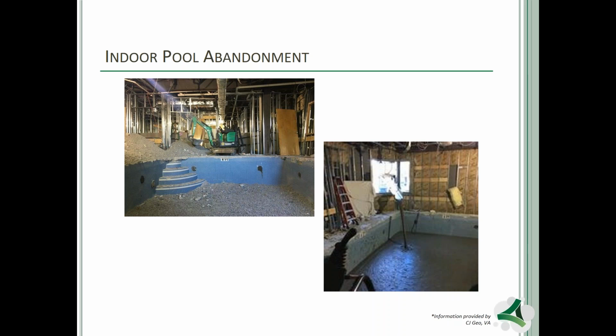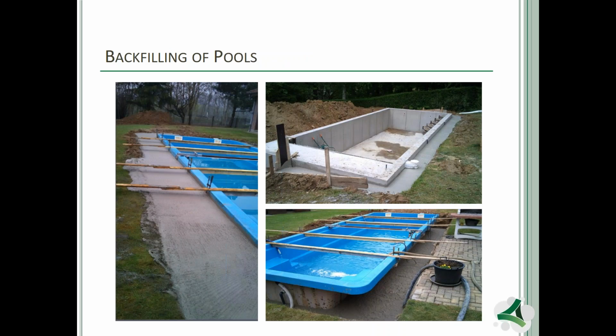Another abandonment scenario was an indoor pool being abandoned from an old therapeutic center, and the installer had to fill it in before the final slab was placed over it for the conversion to a new office building. Personally, I would have kept the pool in my new office, but they decided to abandon it. When you're doing pools, the utilization of cellular concrete is a great way to backfill. Just a reminder that in that scenario, make sure that you fill the water in the pool at the same rate, so you don't have a collapse.